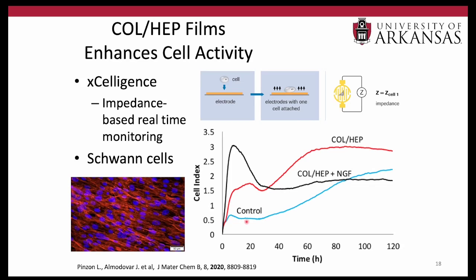In our control surface here, we see that the cells attach and grow, and they seem happy. Then when we add our coatings, we see a very significant improvement in cell attachment. That led to a significant amount of cells growing and reaching that plateau of growth much earlier. But then when we added the NGF, we saw a huge spike in cell attachment, to the point where so many cells attached that they had to detach as well, because there was only enough surface cover. And then eventually it reaches a plateau as well.